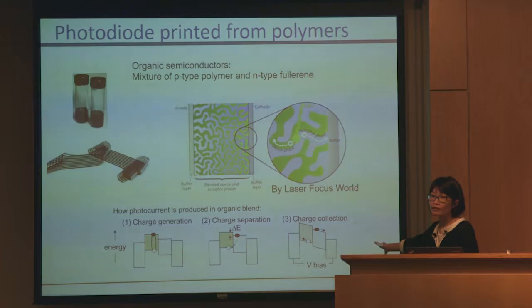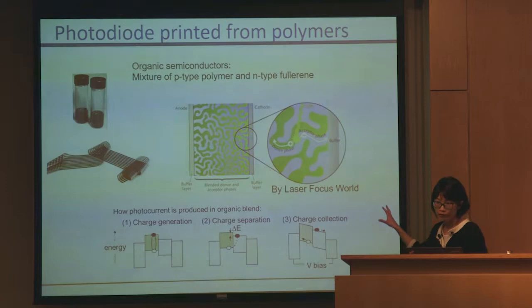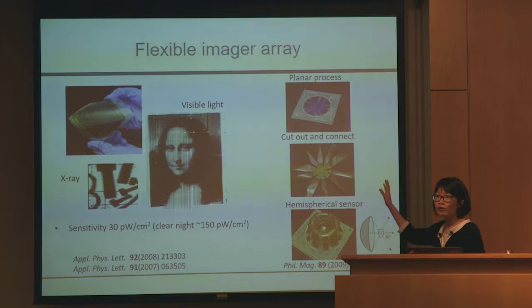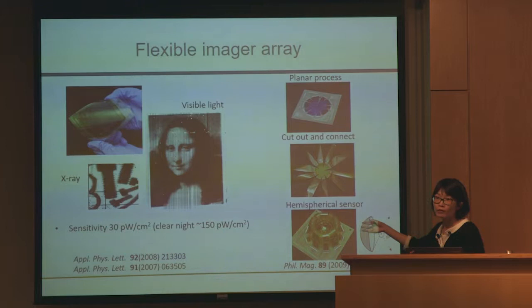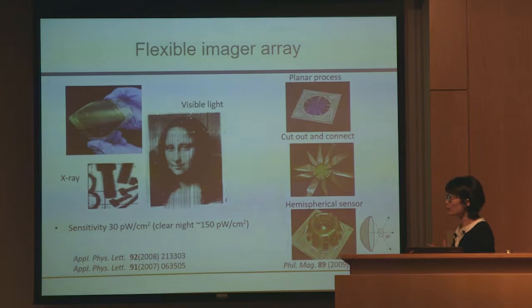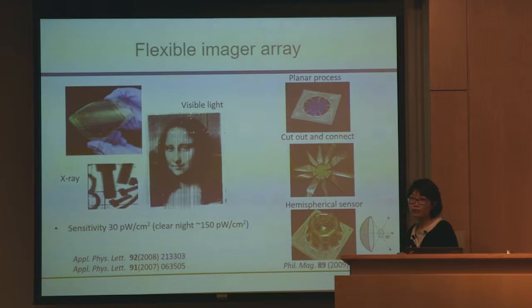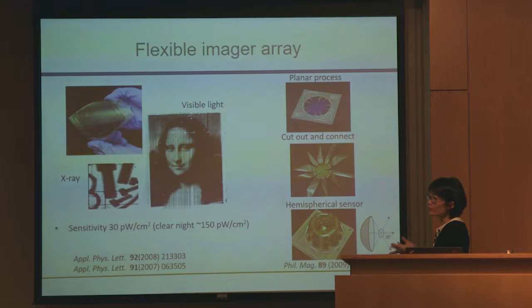And so a lot of people wanted to use this for photovoltaics. It's a big area in our field too. But for me, I'm more focused on the imager aspect of it, so I'm using this for the imaging application. And so now you can see, by putting that material onto the flexible backplane, we could make an X-ray imager and a visible light imager. And the sensitivity of it is pretty good. We could measure 30 picowatt per centimeter squared. That translates in physical terms into being able to image a clear night sky. That's more than sufficient.